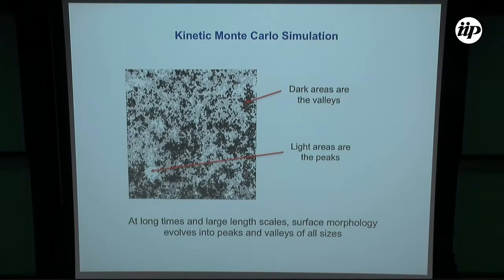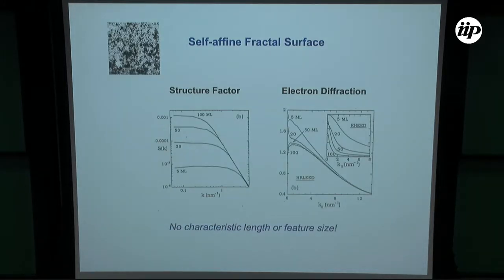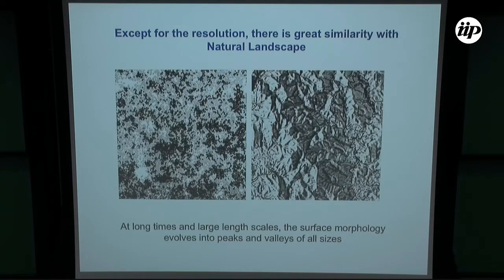This is not that different from what you find in a randomly rough surface, a randomly rough function. If you look at the mathematical structure of these surfaces with things like the structure factor that you would measure in elastic neutron scattering or reflection electron diffraction, what you find